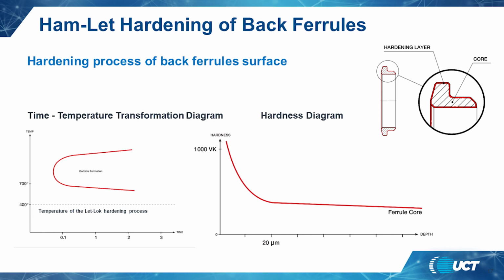For instance, the ferrule must deform elastically and plastically, precisely during fitting assembly, to properly grip and seal the tubing. Its front edge must be harder than the tubing to grip and seal through surface scratches and defects. But if the entire ferrule is too hard, it may not deform properly. Therefore, only the gripping edge of the ferrule is hardened, while the rest has different, tightly controlled mechanical properties. Also, the hardening process must not compromise stainless steel's corrosion resistance. And finally, production processes must consistently turn out defect-free ferrules that hold tight tolerances and maintain metallurgical specifications.